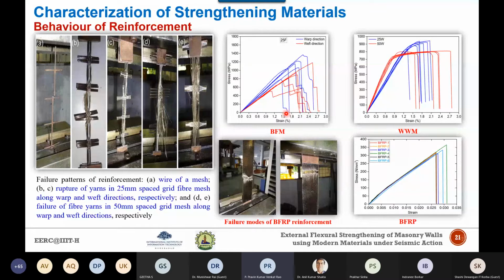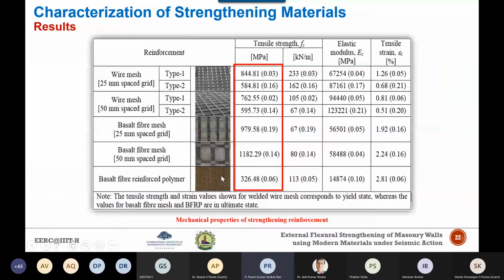And if you see the FRP composite failure modes, the results of BFRP are quite repetitive and the stress strain curves are almost linear right up to the failure. Now next, if you see the test results, the tensile strength is basically obtained by dividing the load recorded by the cross-sectional area of the specimen.